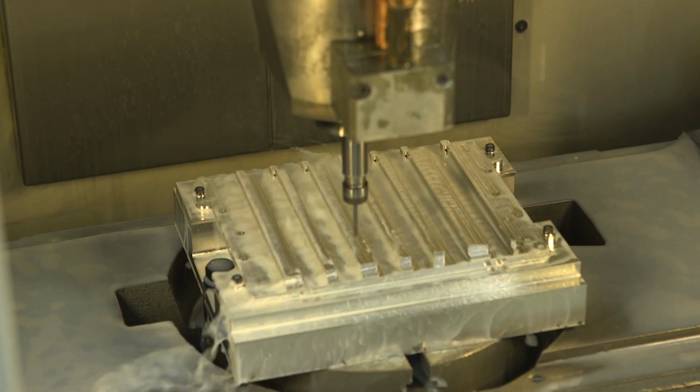Mike, the reaction systems part is a little unusual in that the interior of it is not just structure, it's actually the working surface of this part, so it really matters on the inside. And of course, this is a part that really couldn't be machined by any process. Tell me about what the build was like of making this very unusual part. So with their part, it was a nice part size. It's something you can hold in your hand. For the 10 by 10 build chamber that we have on the Concept dual laser out there, it fit very nicely in the chamber. Beyond that, we had support structures on the bottom of the part, so we were able to bandsaw the part off, and then we can put it in one of our CNC machines to machine the part itself.